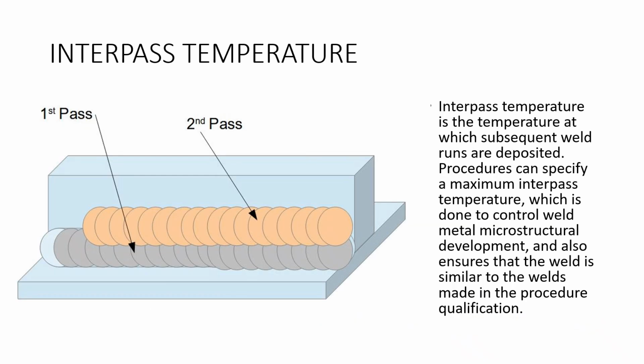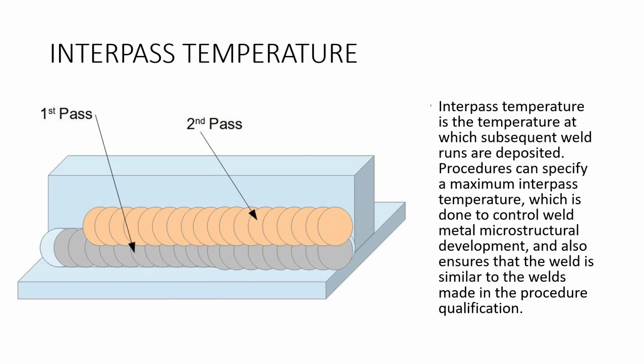Another one we look at is interpass temperature. A lot of materials that we weld, this kind of ties into preheat temperature, where we don't weld on a material unless it's a certain temperature. Well, interpass temperatures are important for different materials. So things like duplex stainless steels, we need to make sure that that material doesn't get too warm when we weld it. We put in a weld pass, and before we put in another weld pass, we make sure it's cooled down below a certain temperature.